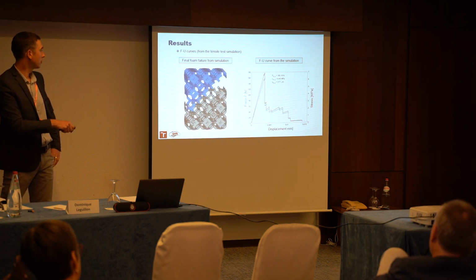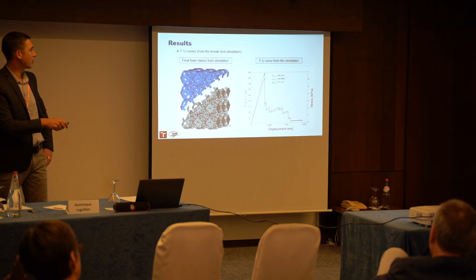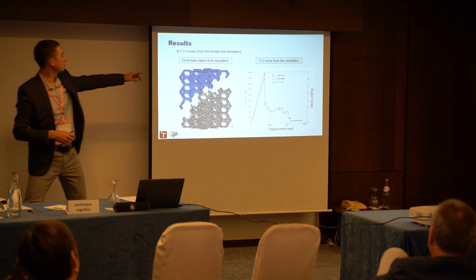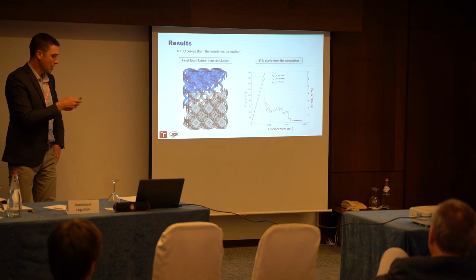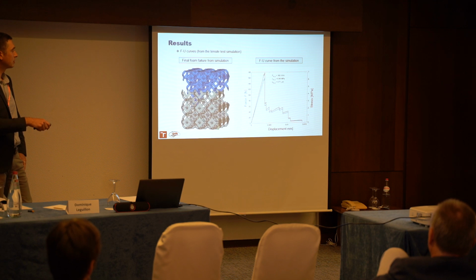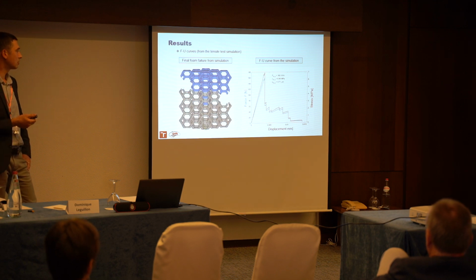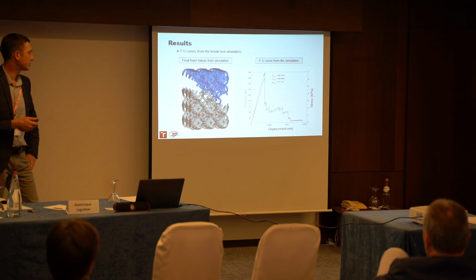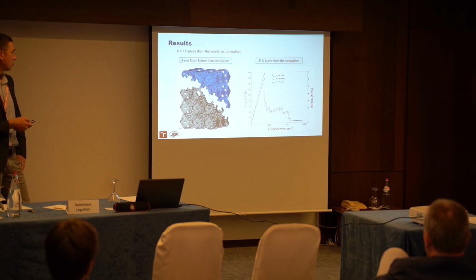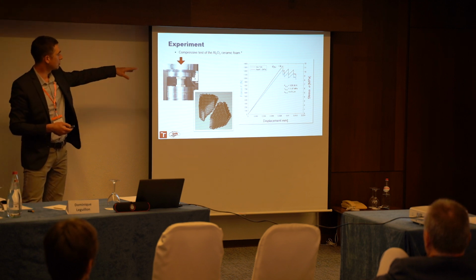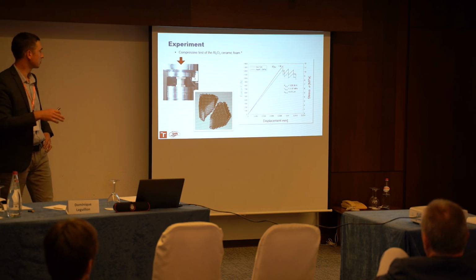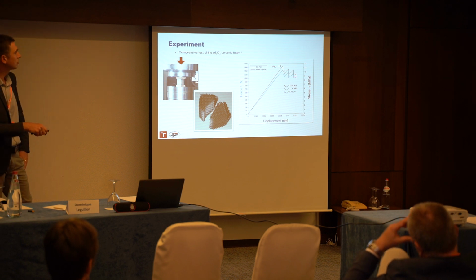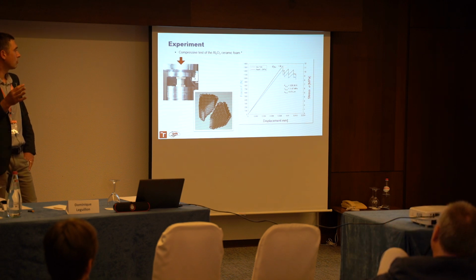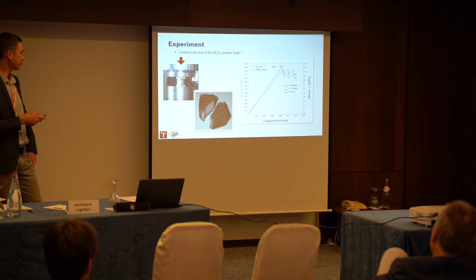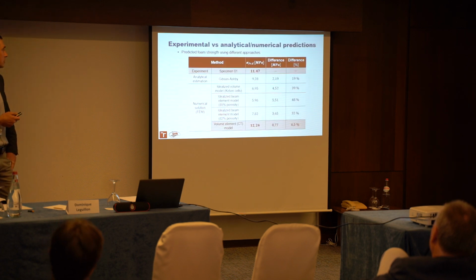So this is the loading curve, force versus displacement or stress, which is force related to the cross section of the specimen. And you see that this maximum force, in this case, is the strength of the foam, which is for us some characteristic. If you take a look at the experiment, the structure was a little bit bigger, there were a bit more cells, so also the force is a little bit higher, but the stress is around 11.5 megapascals. So now let's summarize the result.